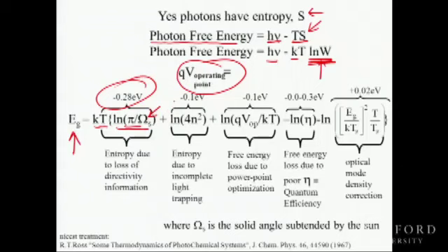If you trap light, that also has an effect because the angle subtended by the sun is even narrower. So if you don't use the light trapping, you lose an additional kT log of 4n squared. There's another tenth of a volt. Then we lose another tenth of a volt. kT log of this number, and this has to do with giving the carriers a reason to go into the wire.